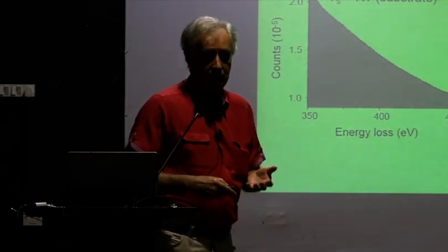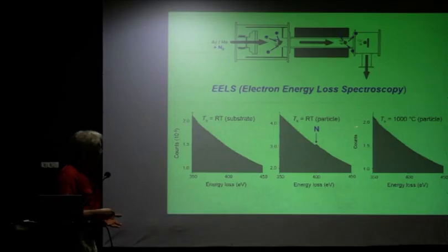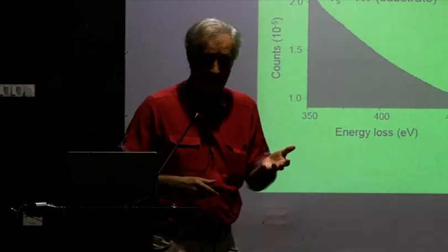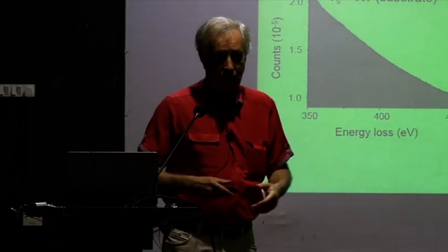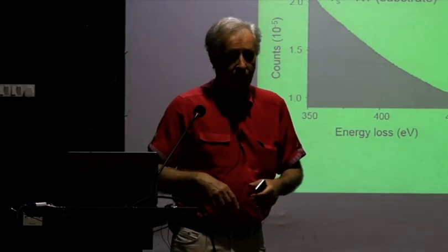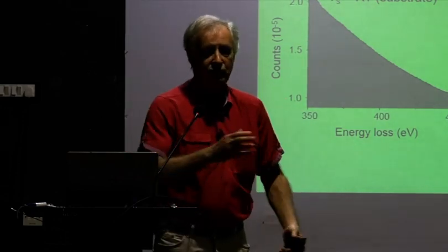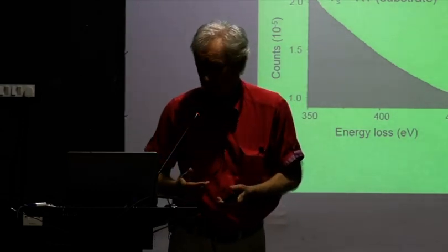And the next thing is to understand whether the nitrogen has gone after that. And when we take the 1,000 degrees centigrade sintered particle, you see here that the nitrogen has indeed gone. So this idea has worked. We nitrogenate the particles, let the nitrogen go, and let the whole thing stir the particles, so nitrogen increases the diffusion. It enhances the diffusion of these things.